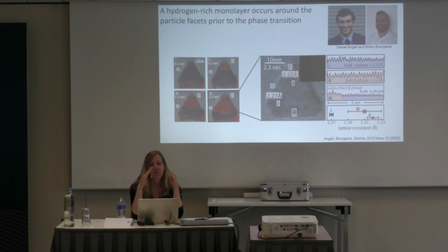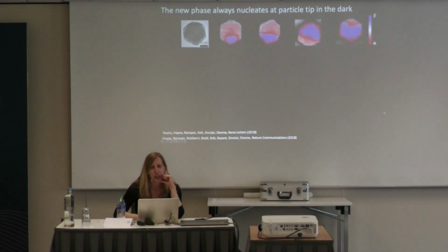And then there winds up being a critical mass of hydrogen at one of the tips, where it starts entering into the nanoparticle and forming this kind of flat phase interface, say a 100 interface. This will be important later on, because what we'll show with light is that we're able to use this subsurface hydrogen to trigger its release with light at the right wavelength, to get more hydrogen when you need it, but turn it off when you don't need more hydrogen or when you don't want to overhydrogenate.